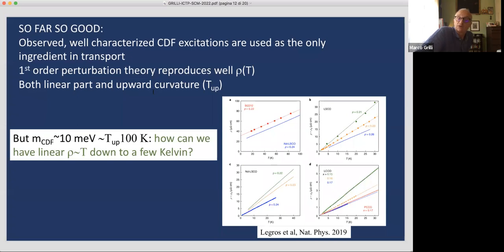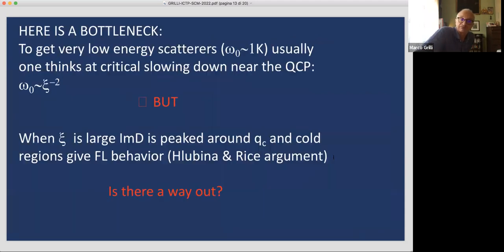But there is a problem, because if you switch on a magnetic field, we know that the linear resistivity goes down and proceeds down to very low temperature, down to 2 Kelvin in the cuprates, okay? And therefore, since the charge density fluctuations have a mass of 100 Kelvin, these fluctuations seem to be unable to explain this mechanism down to the lowest temperature. So we have to think of something more.